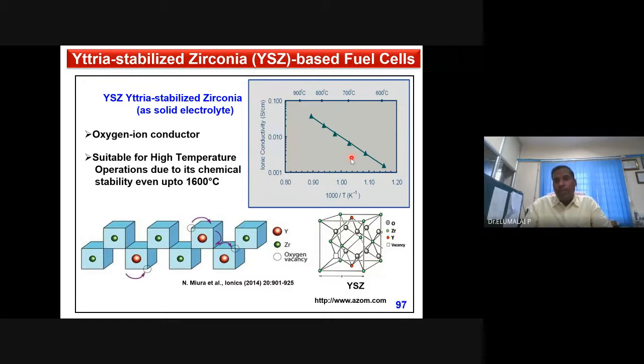How much is the conductivity? This is the ionic conductivity, and this is the inverse of temperature. Okay. So at this temperature, you get at least 0.01 or 0.015 Siemens per centimeter as ionic conductivity. So instead of yttria, there are many other works. Calcium can be used for stabilization. Strontium can be utilized. Magnesium can also be utilized. By considering the price as well as the conductivity magnitude, yttria stabilized zirconia is the most popularly used solid electrolyte for SOFC applications, and also for air fuel sensor applications.